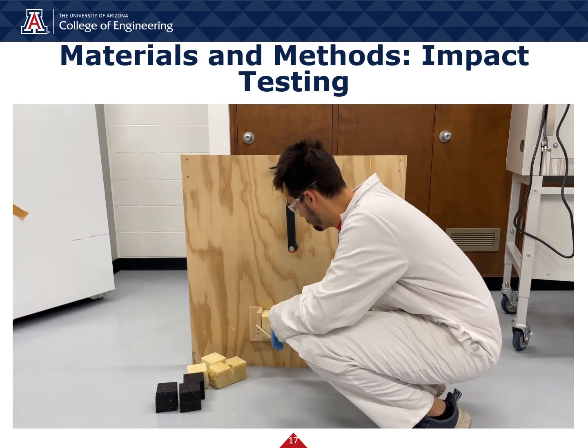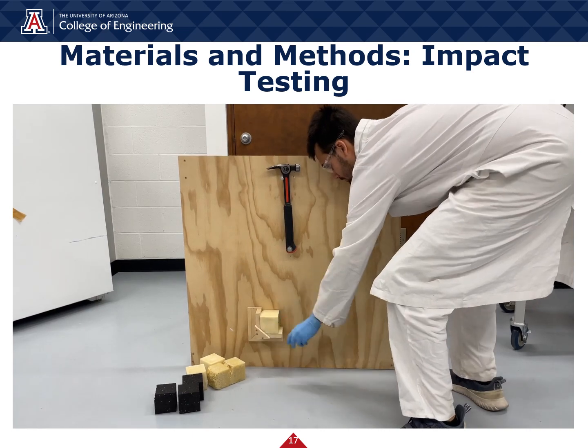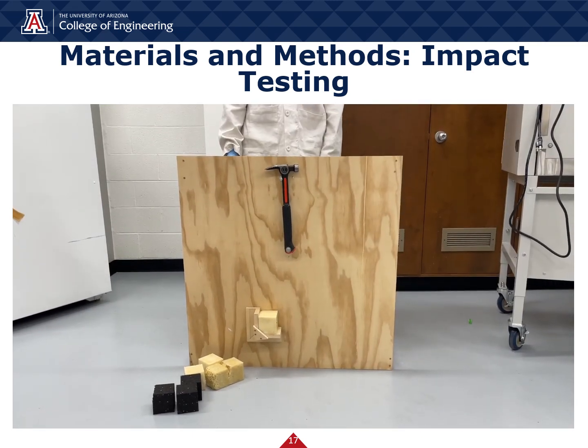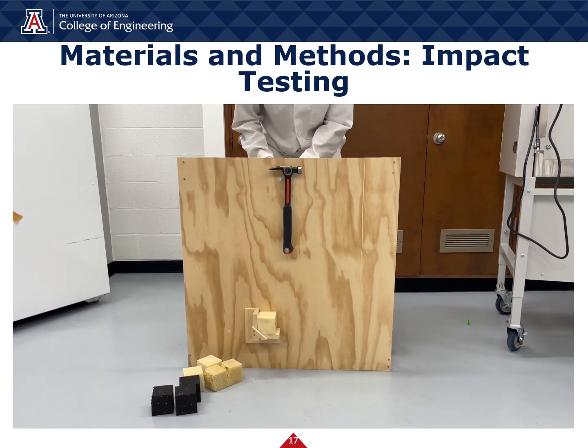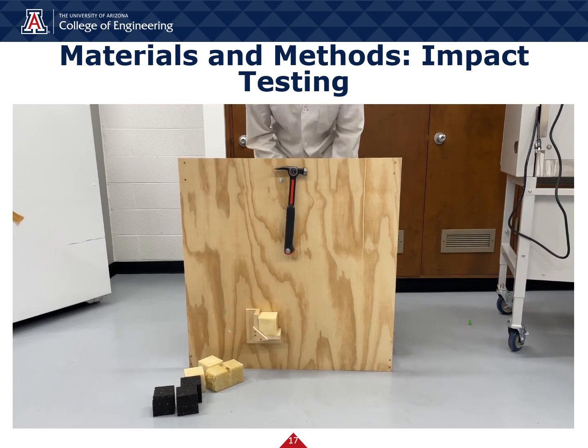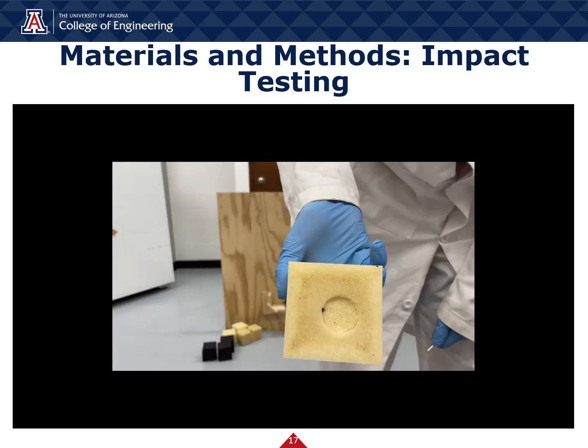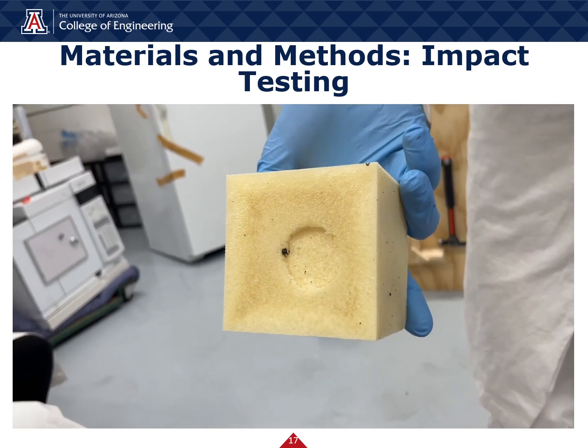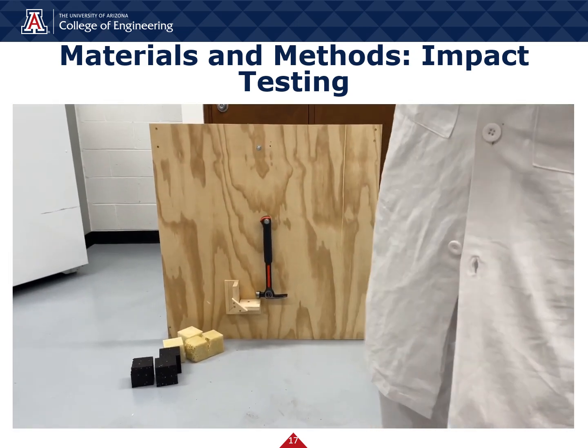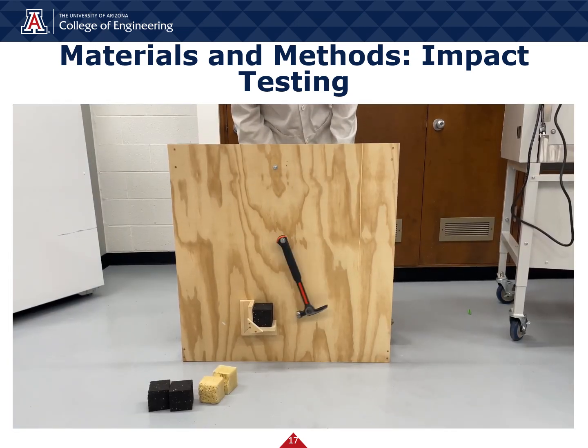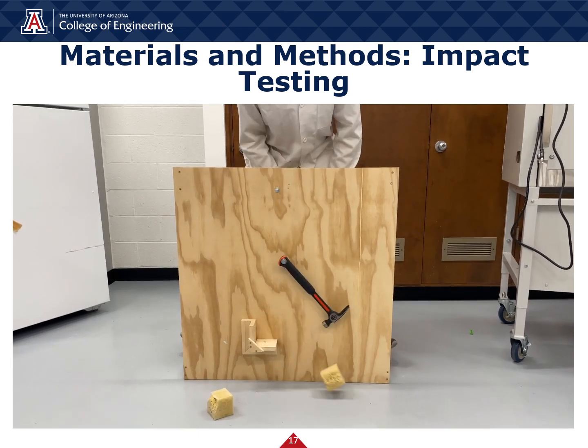As for the impact test, the hammer sits in a resting position, which is approximately 180 degrees from its striking position. Once the apparatus is stabilized from the back, the pull pin is taken out, which allows the hammer to convert potential energy into kinetic energy and strike the test foam piece. The hammerhead strikes the foam piece at a constant area and force. The video shows indentation of the foam kit and lack of indentation of the EPP and custom foams.